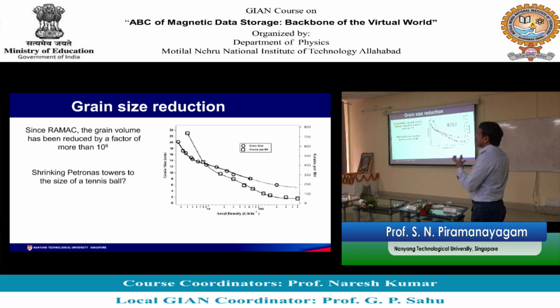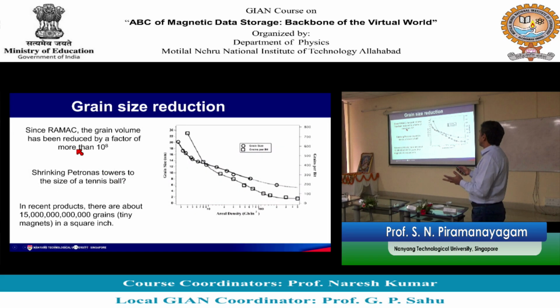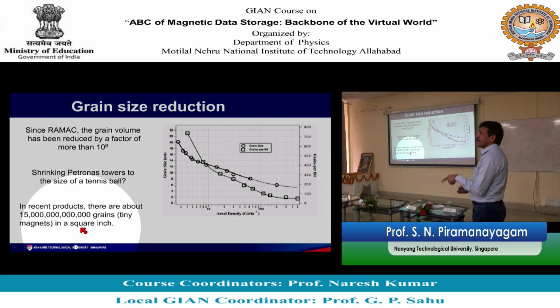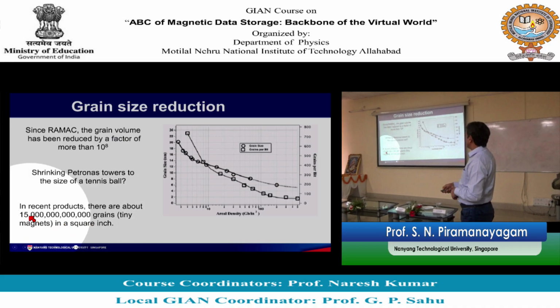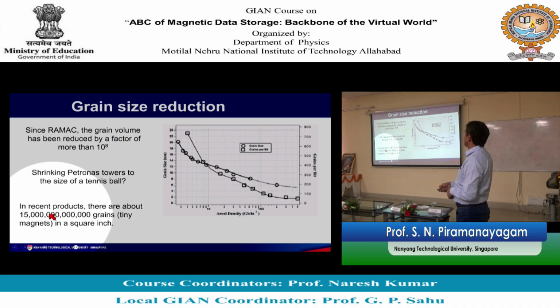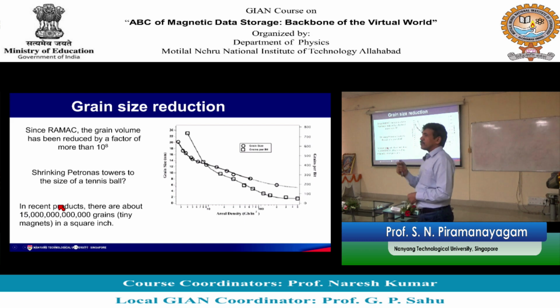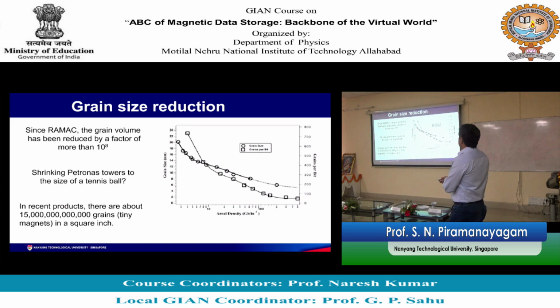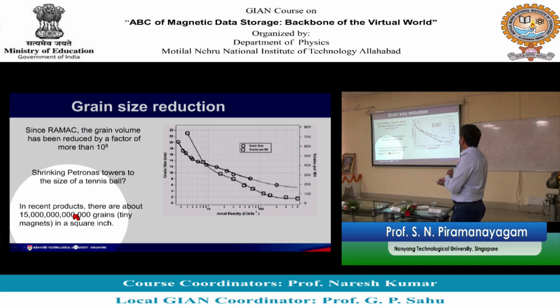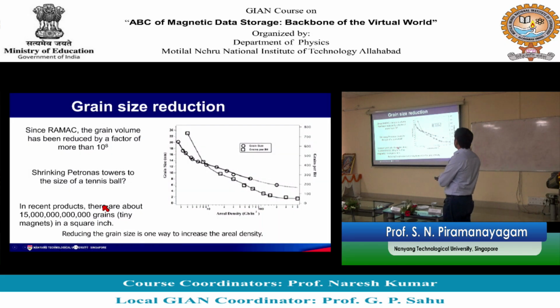So, if you compare the volume, the grain volume has reduced so much that it is like shrinking the volume of Petronas towers to the size of a tennis ball, something like that. In recent products, if you take a square inch, we have like 15 trillion grains within 1 square inch. So, the grains are so small that we can pack 15 trillion grains in a square inch. So, that kind of growth has happened. So, reducing grain size is one way to increase the areal density.